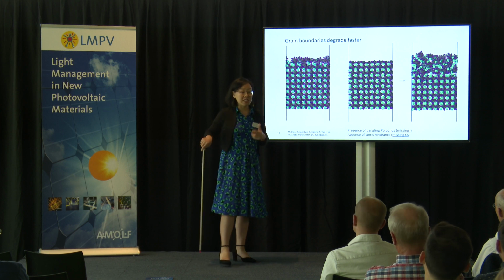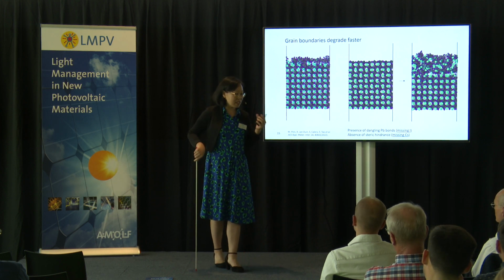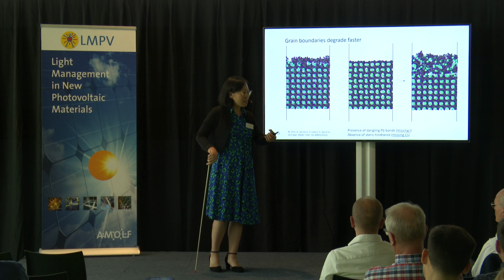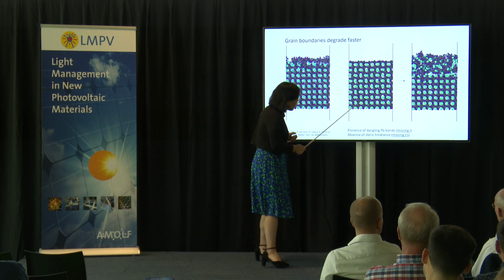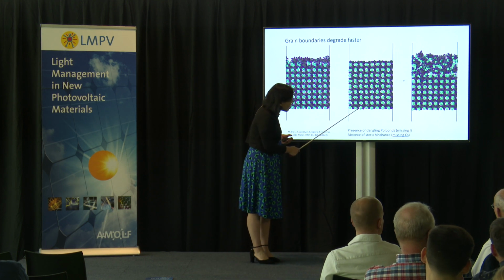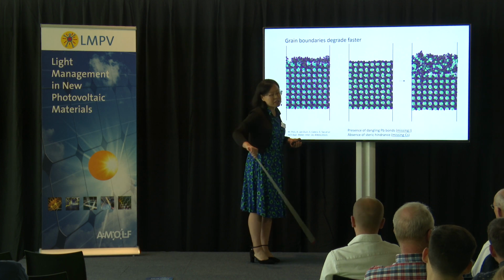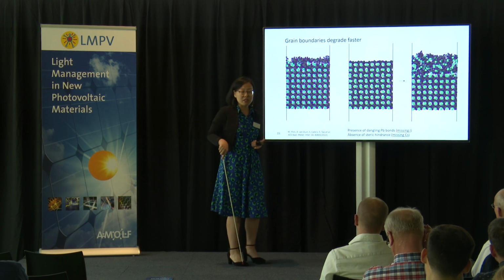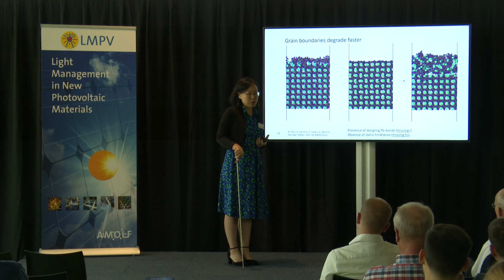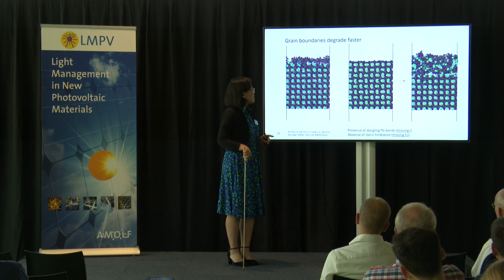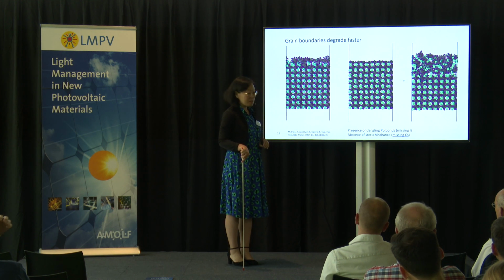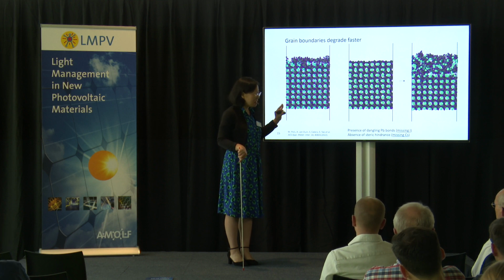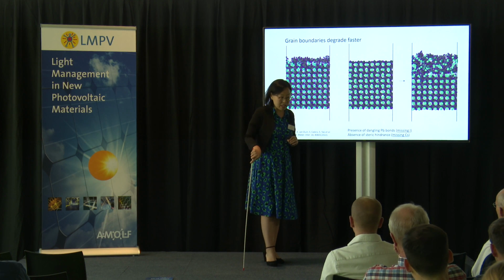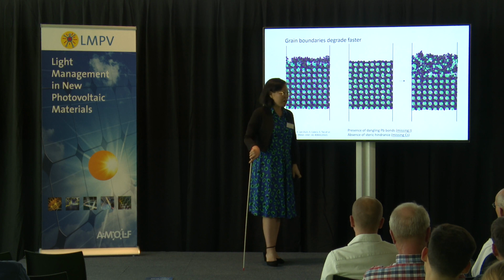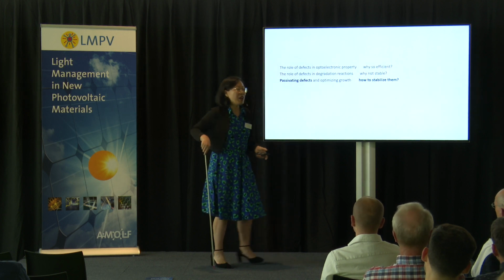Another advantage of this surface is this cesium. The cesium also does not form a covalent bond, but it's a big atom, it's heavy, and it has electrostatic interaction. Most importantly, it holds the iodide here and does not allow it to move around. This is very, very important to stabilize this surface as well. So using this very simple system model, we get this understanding of where this chemical instability comes from. Now you can guess what we do next.